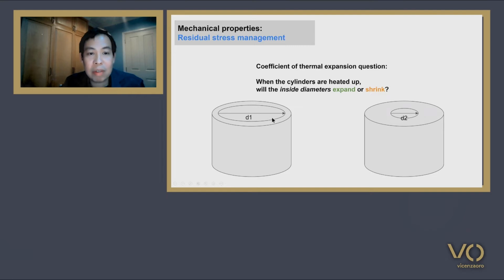Well, the question is, when we heat up this cylinder, the expansion happens, but would the inside diameters expand or shrink? On the left-hand side, it's quite obvious that as the cylinder is heated up, the D1 value, the diameter, would expand because the material expands right around here. But for D2, there are two things at play here. The outer circle would definitely expand, but the inner circle, the expansion itself could be towards D2. So this is the sort of fun experiment that we have to do in order to manage the thermal expansion and the residual stress.